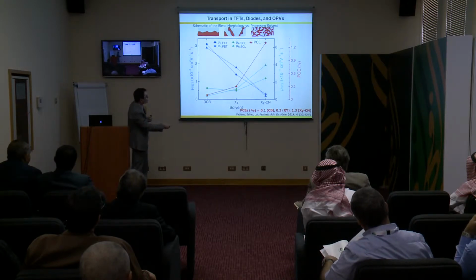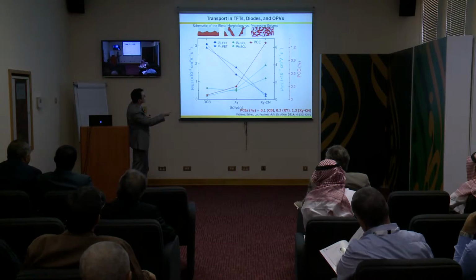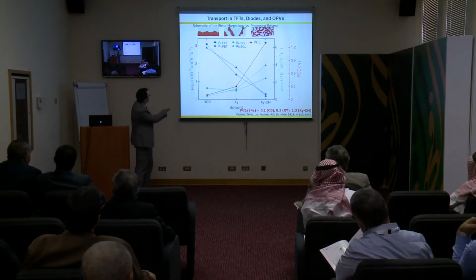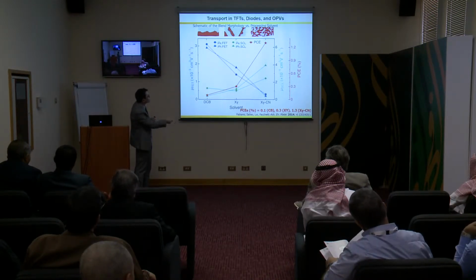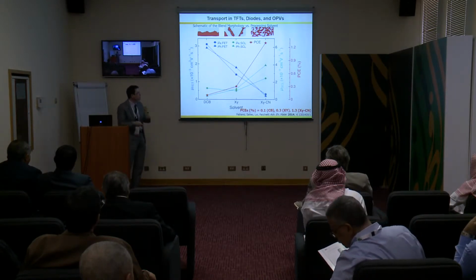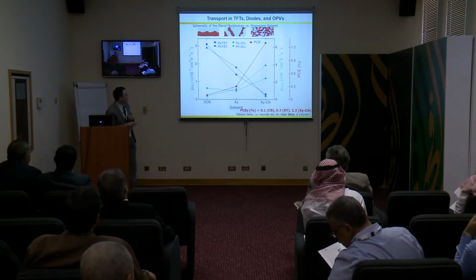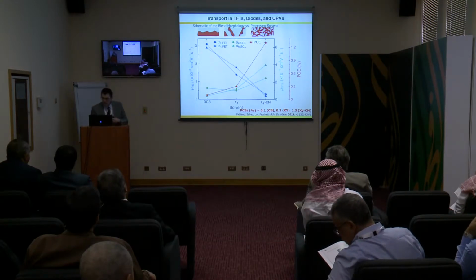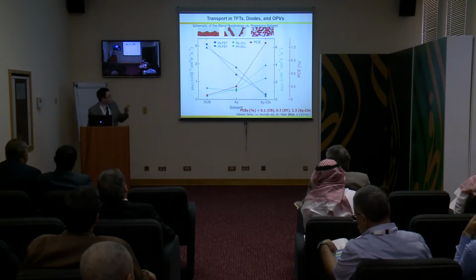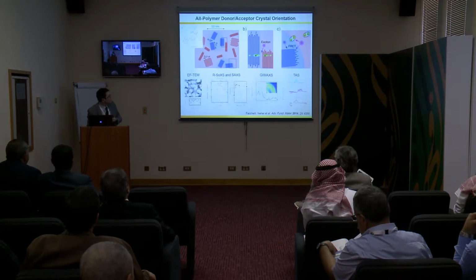When you start using a better solvent, which mixes the two polymers a little better, the field effect mobility drops, the diode's mobility picks up, and the efficiency starts increasing. So we went from 10 to the minus 3 to on the order of 1%, just by changing the processing a little bit.